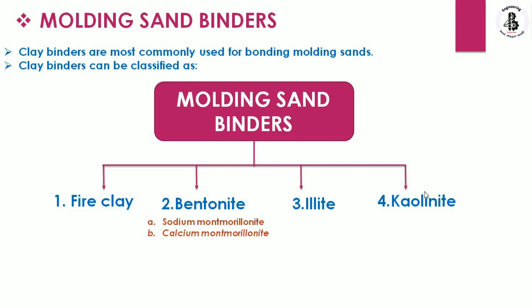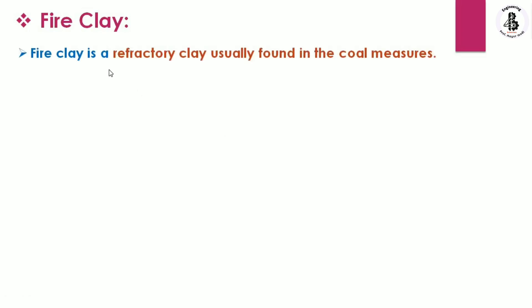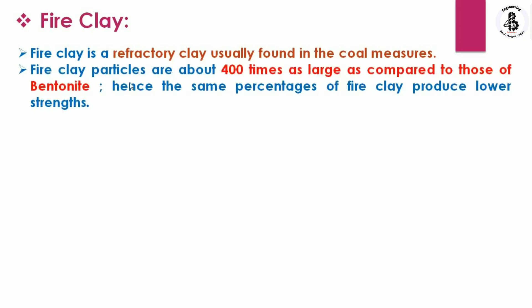Fire clay is a refractory clay usually found in coal measures. Fire clay particles are about 400 times as large as compared to those of bentonite, and hence the same percentage of fire clay produces lower strength.